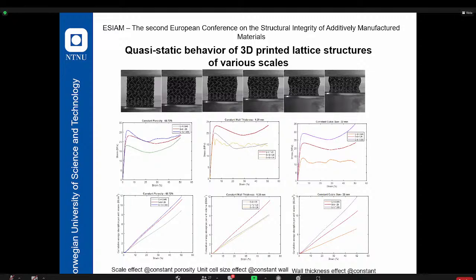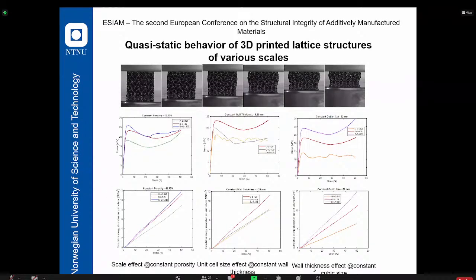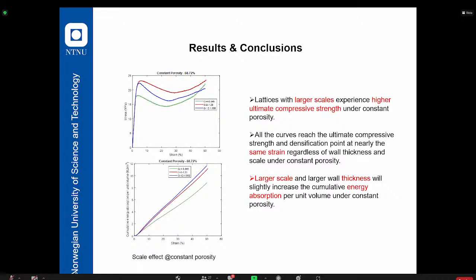And then all these lattices went under static compression at a constant compression rate of 2 millimeters per minute. Then we calculated the stress strain curve based on the force displacement, and we can get some results. For the lattices under constant porosity, the lattices with larger scales experience higher ultimate compressive strength. Also under constant porosity, all the curves tend to reach the ultimate compressive strength, and the densification points are nearly the same regardless of the wall thickness and scale. Also larger scale and larger wall thickness will slightly increase the cumulative energy absorption per unit volume under constant porosity.